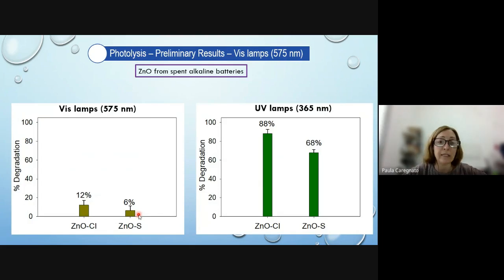Okay, and finally, these are the results of photolysis with the zinc oxide obtained from spent alkaline batteries. Using the visible lamps, we can see that the percentage degradation of the contaminant is very, very low. They are inside the error. But with the UVA lamps, the percentage of degradation of carbamazepine with both materials is quite good.